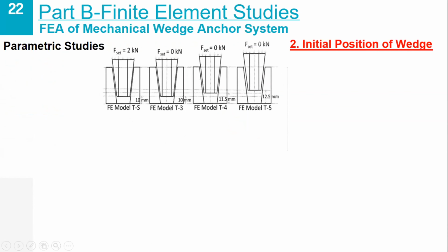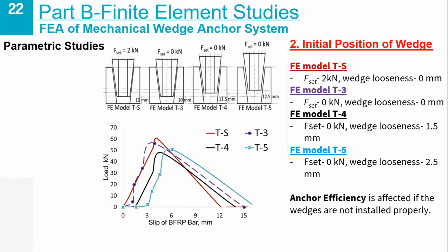The second parameter that has been investigated is the initial position of the wedge. So 4 different initial position of the wedge as well as the setting load has been investigated, and it can be seen that the anchor efficiency is affected when the wedges are not properly installed. So basically this red line shows the properly installed wedge, and you can see that there are no initial slips that are observed in this anchor, and also the slightly higher strength has also been observed for this wedge.